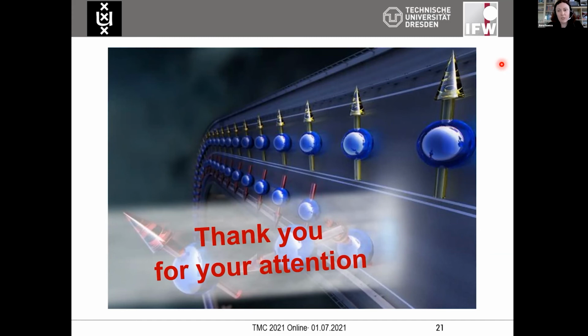And as for the variation of the magnetic properties, so yes, it exists to some extent. We try to do it deliberately, so to produce samples that are mixtures of two phases. And it was possible to see slight variation of the TC for one phase, and then already a superposition of two different transitions, indicating that we have two different phases. So at least there is no smooth transition in the critical temperature and the general way the magnetization curve looks between the phases.